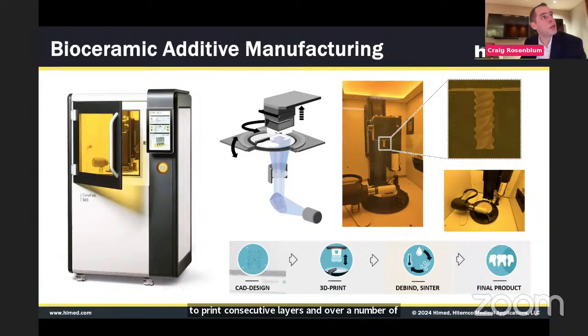we can print. I realize I'm covering the final product in the upper right-hand corner of the screen, but this, of course, would be an orthopedic screw that was 3D printed, in this case with hydroxyapatite. But one might be interested in printing with a biphasic calcium phosphate, where perhaps there's a gradient along the screw depending on where the more stable hydroxyapatite would be desired, as opposed to a tricalcium phosphate, which is going to be more resorbable. So there's a lot of interesting technology that could come about from this.